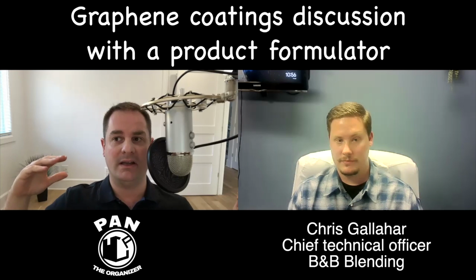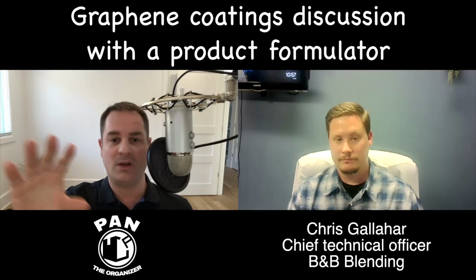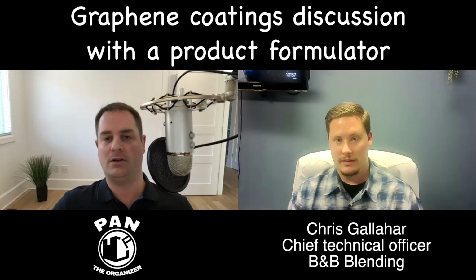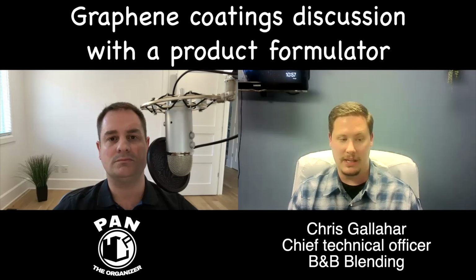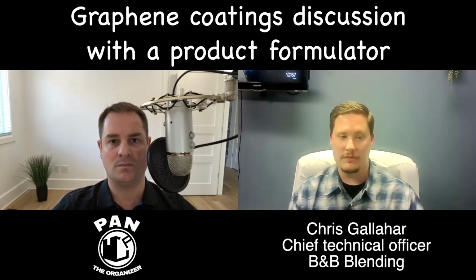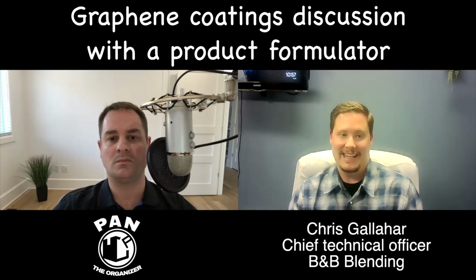So is there such a thing as lowering the surface temperature as well? Or in the products that you formulate, is that not even a factor? That has nothing to do with the water spotting? We did some brief measurings like that and we threw it out almost immediately because, again, individuals need to understand you're not applying this on a macro scale. These are nanomolecular surface modifications. The coating film is far too thin, in my professional opinion, to offer you any sort of thermodynamic benefit. So people, like David was saying, people have been shooting it with IR guns and making their claims. That's realistically not doing anything.